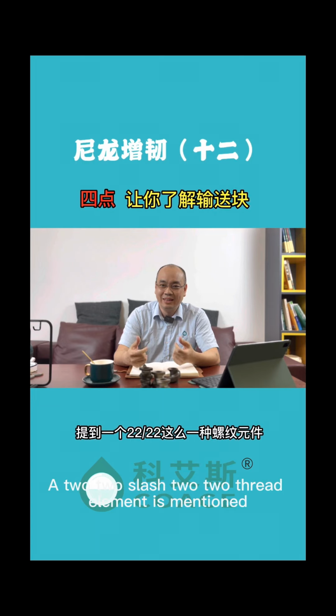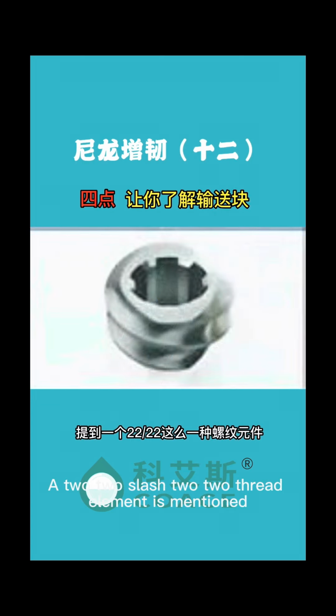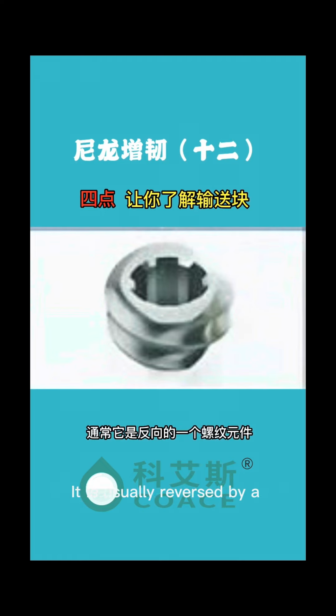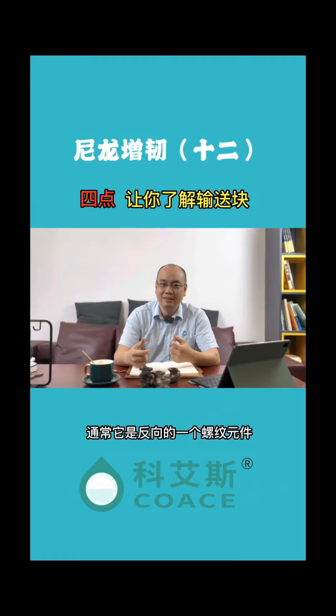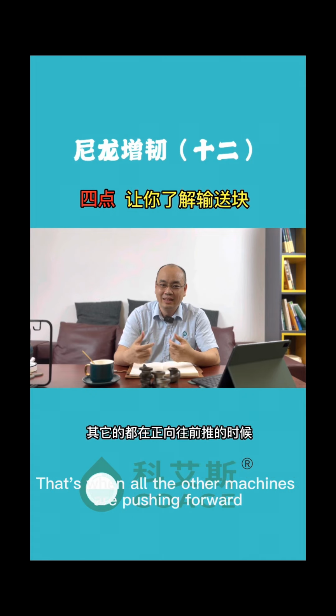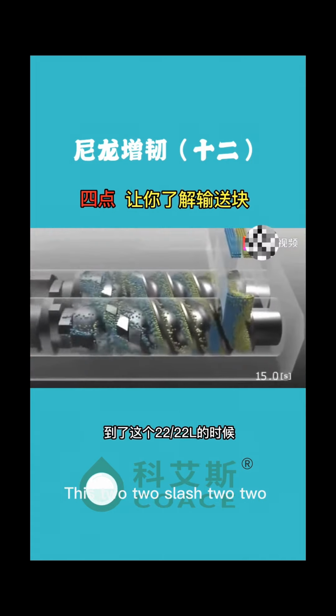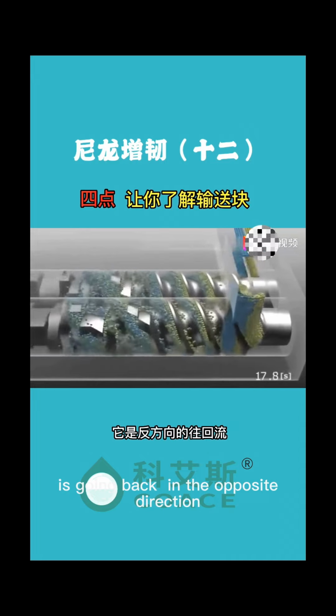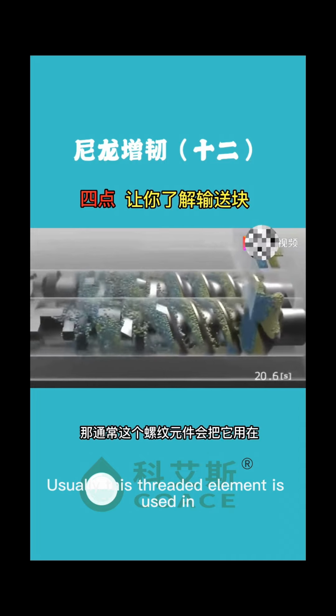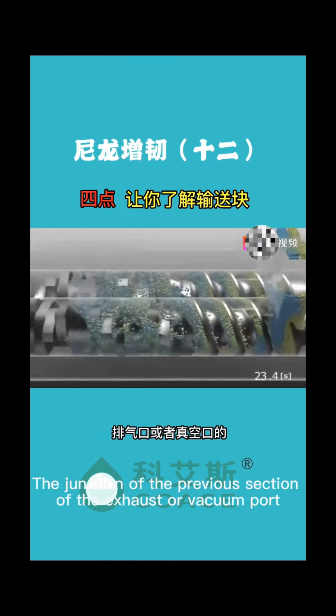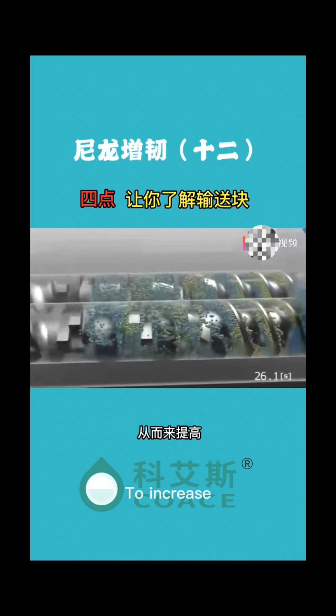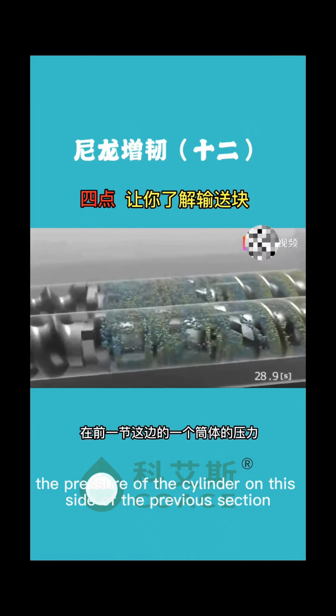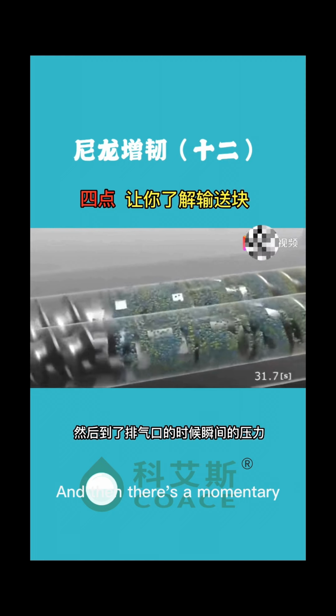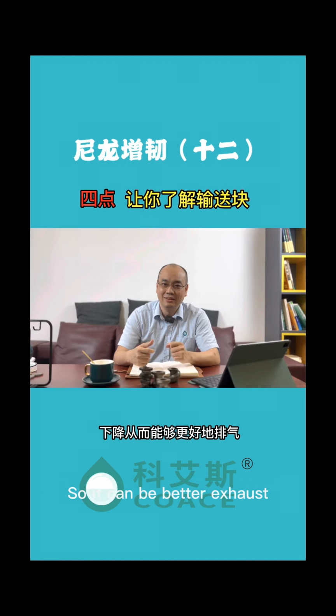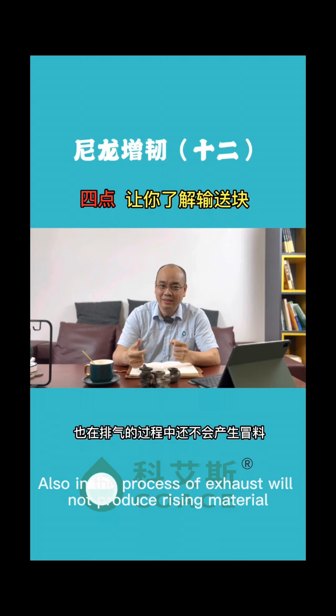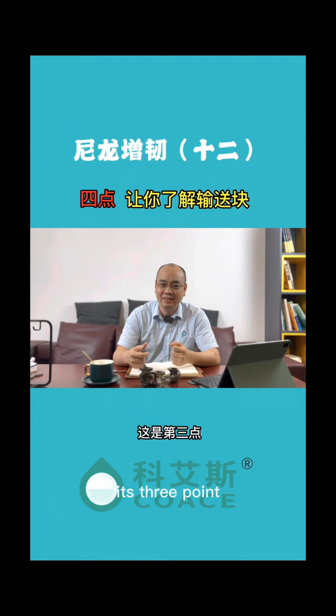There's more. A 22/22 thread element is mentioned. This element is followed by an L. It is usually a reversed threaded element. That means when all the others are pushing forward, this 22/22 is going back in the opposite direction. Usually this threaded element is used at the junction before the exhaust or vacuum port, to increase the pressure of the barrel on the section before it. Then there's a momentary pressure drop when you get to the vent, so it can exhaust better. Also, in the process of exhaust it will not produce rising material. That's point 3. Point 4.